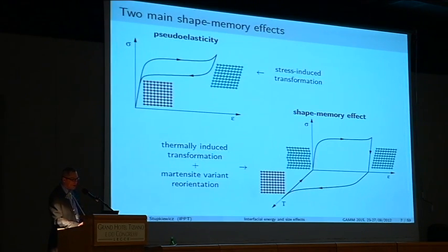of crystallographic lattice. So we have these two main shape memory effects, the first is pseudoelasticity, and I will say a few more about that. So you have material at relatively high temperature, you start loading, it responds elastically, at a certain moment something happens, which seems to be like plasticity, but it's not plasticity, it's phase transformation. So you load until you completely transform your material, so then there is something like apparent hardening, and the response is again elastic, but in the new phase, the phase that you have induced by the stress-induced transformation. But what is also peculiar, when you unload, you have a reverse transformation, so that in the ideal world, you come back to the initial state with no residual strain.